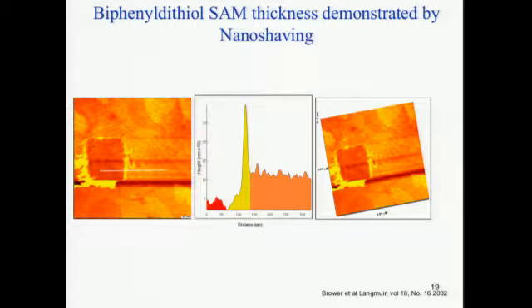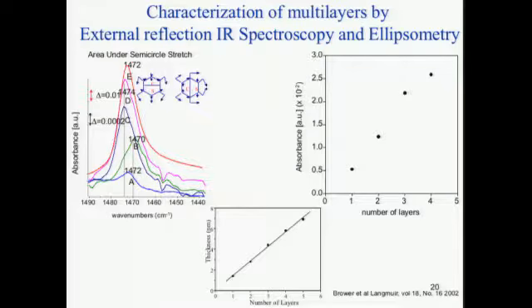And of course, like I showed you earlier, you can look at what the gold structure is, because that's well characterized by STM. So you know when you hit the gold versus whether you're still in the monolayer, you can get an actual height measurement. And so that's important.